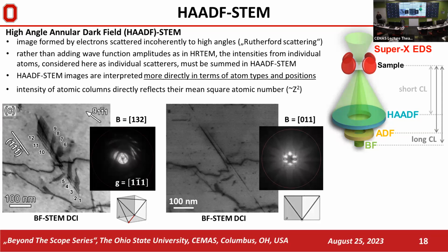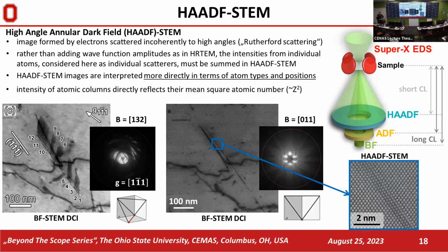That's a very big difference from the practical point of view compared to what we used 10 years ago, phase field high resolution TEM phase contrast, where you had to do simulations to support and to find out where your defect and your stacking sequence change in your complex defect was happening. So here, from a practical point of view, we were doing bright field STEM DCI. We just tilted to zone axis, changed the camera length, and magnified, and in a few seconds, you're getting atomic columns of the defect. So that's a huge practical advantage.